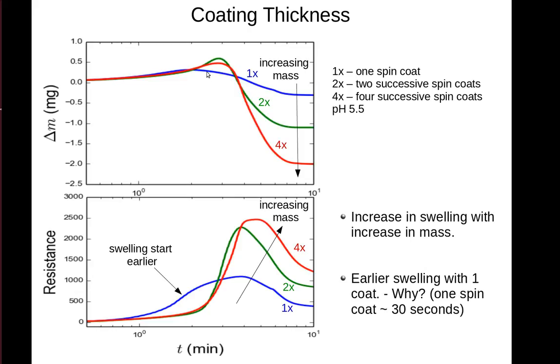However, the peaks stay roughly at the same time, which makes some intuitive sense since the polymer and the buffer solution are the same. If we look at the resistance, we do see a slight shift to lower times for the 1x spun crystal, for the lower mass. It turns out this is due to a drying effect. When we only put one coat on there, there is minimal time between the coating and the subsequent dissolution, whereas when we spin coat multiple times, each spin coat gives the underlying layers more time to dry.